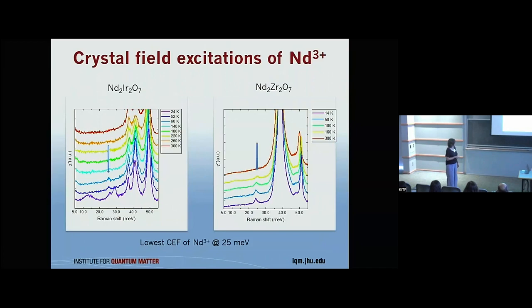We observe the crystal field excitations with Raman scattering, and here I would like to advertise it. A lot of times it's done with neutron scattering, but Raman scattering is the cheapest way to measure crystal field excitations in insulating systems. So we observe the transition between the ground state and the first excited state. We agree with neutron scattering down to a couple of milli-electron volts. It's at 25 meV. We observe it well above the temperature of the magnetic transition in neodymium iridate, and then it overlaps with the magnon band of iridium. Measuring neodymium zirconate confirmed that yes, that's the crystal field transition, and that's how it looks.